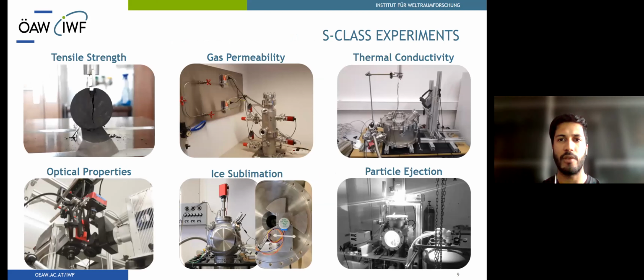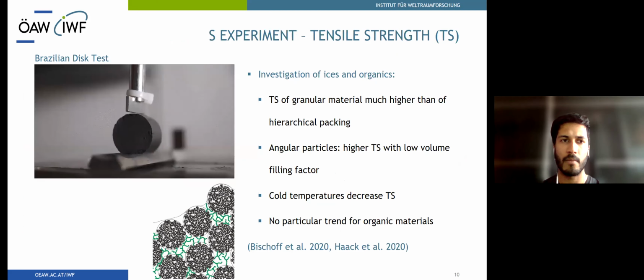In the following, I would like to present a brief overview of the individual S experiments that have been performed so far. The first one is called Brazilian disk test, which is used to determine the tensile strength of brittle media. This is done by measuring the force required to break a standardized disk of compressed material, as shown in this video. The main findings of these experiments were that granular media, especially those with angular grains, have a tensile strength that is much higher than that of hierarchically packed material. Hierarchical packing means that the smallest particles form intermediate agglomerates, which themselves can pack like large particles. Cold temperatures tend to decrease the tensile strength, while for organic materials, no clear trend was found.